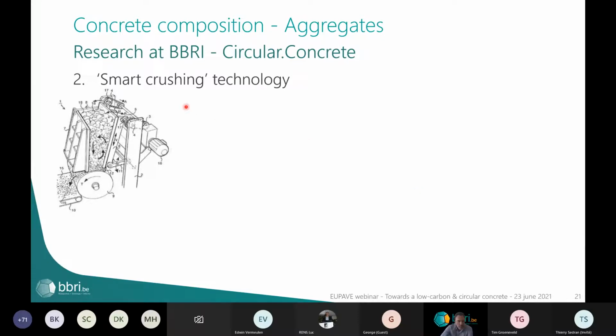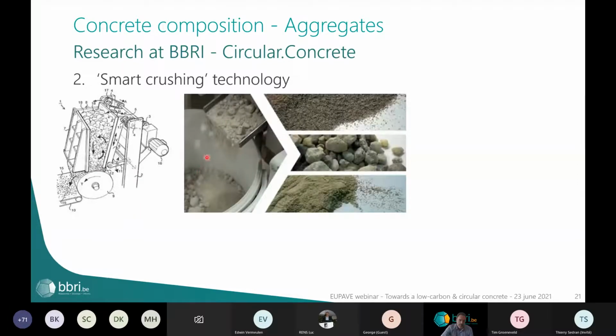investigation. We also looked at the smart crushing technology, in which a special equipment is used to break, and not only break, but it's a combination of different operations to get the debris of the concrete to obtain the original components, so the original aggregates without any mortar still adhered, or very little mortar still attached to these aggregates, sand, and also a fine filler particle, which can then be used in the cement production, or even as such in concrete production. So this is the theory.